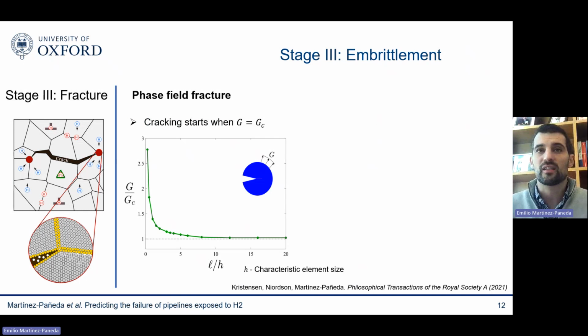And we have shown that this is the case not only theoretically, from a purely mathematical point of view, but also from a practical point of view. So if you run a finite element simulation with what is called a boundary layer model, where you prescribe a remote K, basically, if cracking starts when G, the energy release rate, reaches a critical value, it is the same thing as saying that cracking will start when the stress intensity factor reaches a critical value, the fracture toughness, right? So we know the relation between these two.